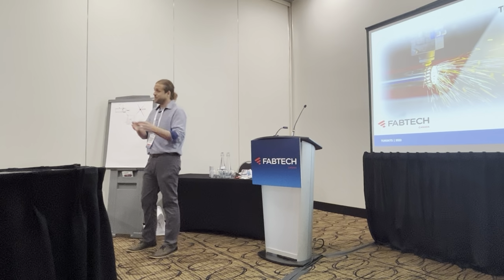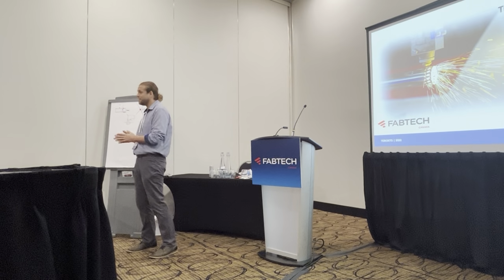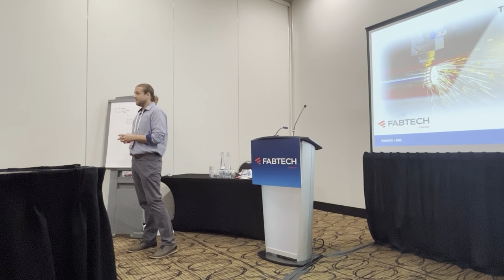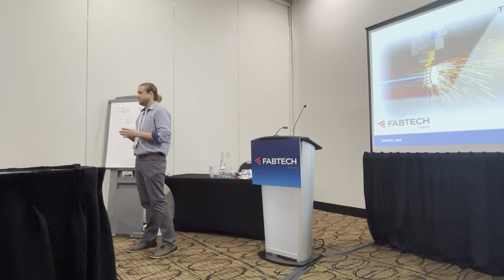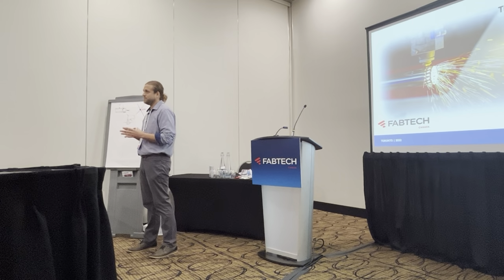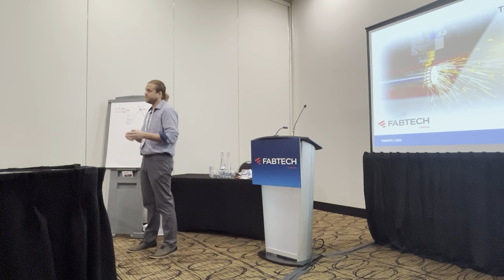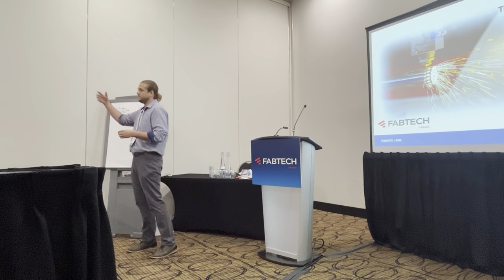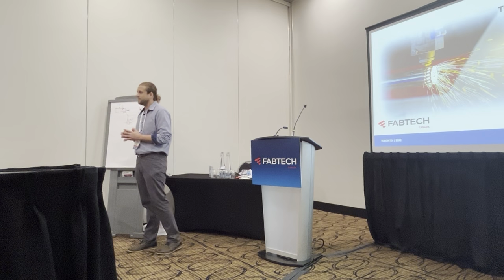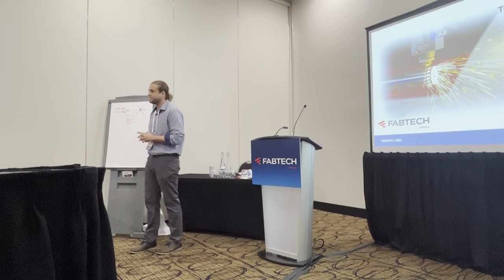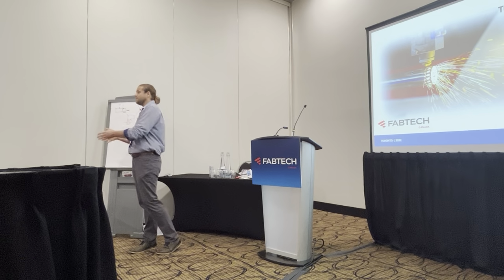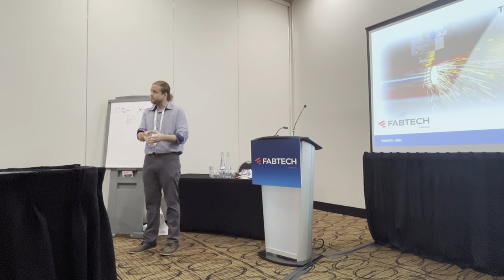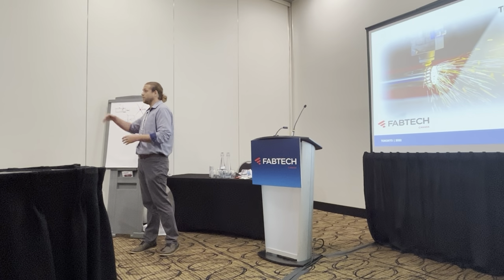But as you get to your thinner materials, like 065, 049, you don't want to cut with a CO2 laser, because it's probably 10 parts to one at that point. That much faster. Because you're talking 100 and some inches per minute on the CO2 to 1,200 inches per minute on the fiber cutting with nitrogen. But if you have the ability to get a CO2 and start bringing in some business, I would never hesitate while you wait for a fiber.